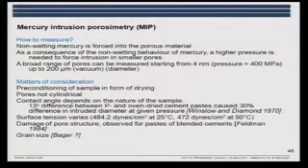And then the pores are not cylindrical in the material we are looking at. The contact angle depends on the nature of the material. And there's a 13 degrees difference between different materials which have been dried, the so-called P-dried and oven-dried samples. And that causes a 30% difference in the intruded diameter. So it's not just peanuts.